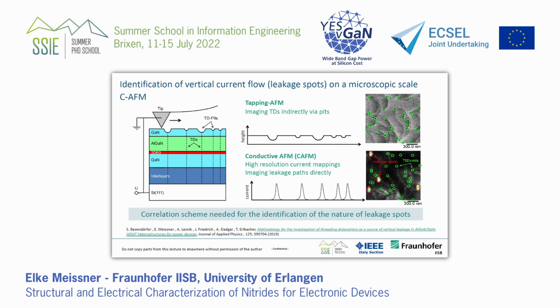And what we see, we make tapping AFM, we see this depression at the surface, we see just a surface profile, we identify dislocations at certain places, and now we run the current through it, observe the same place, but what we image then is current flow paths. So let's say locations where we have prominent current flow, higher than the background, and these are such places. And then we started correlating it with the places of dislocations. Here you see we have these, we call them leakage spots, the big red ones, and we observe whether there is a dislocation or not, or many dislocations, and what they do, and we try to identify the nature of such dislocations or such defects that are underneath such leakage spots.